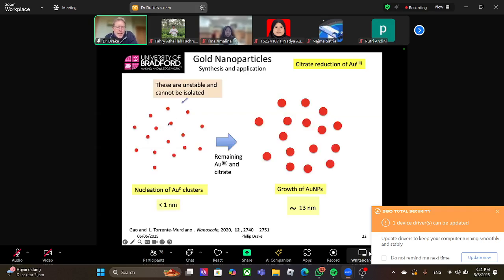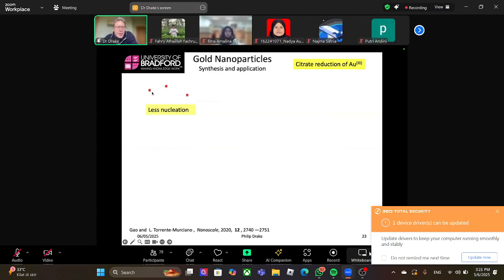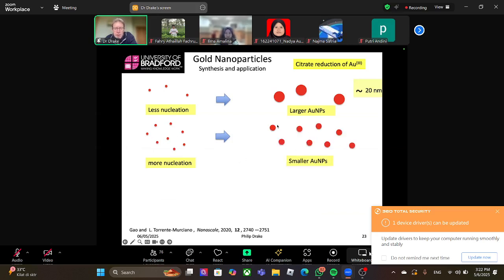So particle synthesis is made from nucleation and then growth. And this is the key to all nanoparticle production, controlling the nucleation and controlling the growth. That determines the size and shape of your particles. If we have fewer nucleation sites, same amount of gold metal, we're going to get bigger particles. All the gold will form just 3 big particles. If we have more nucleation sites, the same amount of gold will now coat all these, giving you more nanoparticles of a smaller size.